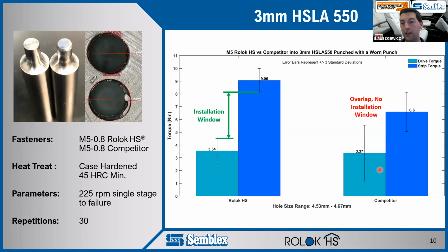Now you're going to see some comparison data here. If you remember that curve early on, that first low peak, our drive torque, is the light blue bar. That higher peak, that failure torque, is the dark blue bar. Now we tested across a hole size range, and this was the tolerance on the hole given to us by our customer. So for thread rolling screws, you're going to have a higher drive torque when the hole is smaller because you need to move more material. So what that means is that these light blue bars, these drive torque numbers, come from the small hole size.